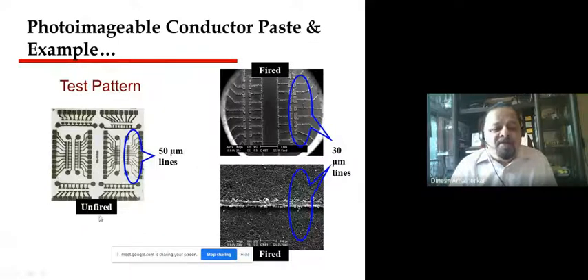We have made a test pattern here. This is unfired, meaning not heated sample. You can very clearly see 50 micron lines. After firing, that becomes 30 micron. So this is probably impossible by traditional classical thick film technology, where you can get a maximum of 150 micron, not even 100 micron. Here, it's easily possible, and we can get 30 micron. This is our own test pattern.